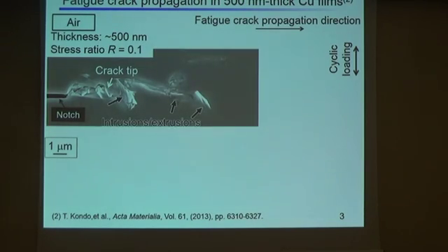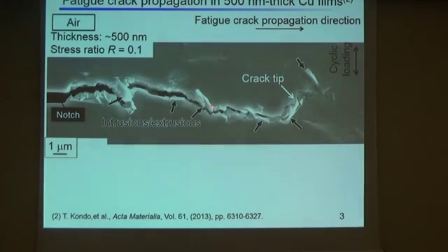We previously conducted fatigue crack propagation experiments in 500 nanometer thick freestanding copper films. And this slide shows intermittent FESEM observation results of fatigue crack propagation behavior in air. By applying cyclic load, intrusions and extrusions were formed, which penetrated the film in the thickness direction ahead of the crack tip. And then this fatigue crack propagated through these intrusions and extrusions.